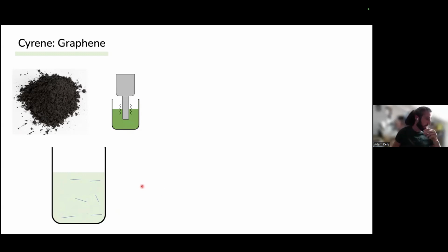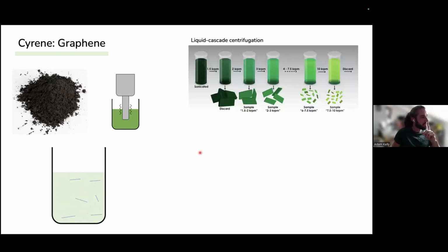And ideally, we would like to produce monolayer rich dispersions. Now, the easiest way to do this is using liquid cascade centrifugation, where we take this sonicated stock directly out here, we centrifuge it at a low speed, and this will contain all of the unexfoliated material. We discard this, and then we take the supernatant up here, we centrifuge that again at a higher speed. Then we'll have the sediment down here that will contain nanosheets with a certain length and a certain thickness.